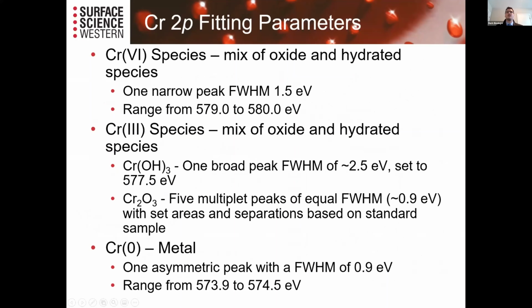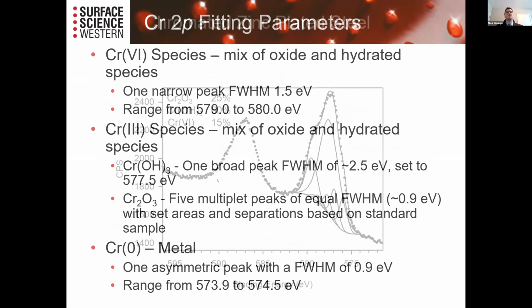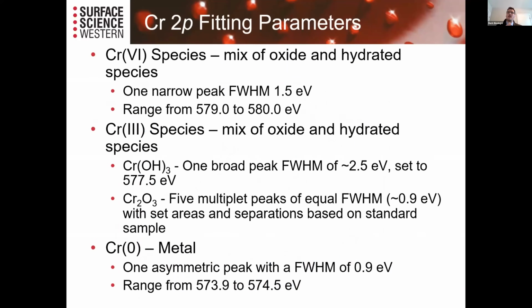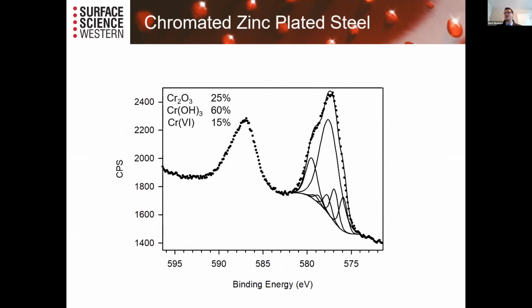For the chromium 3 species, for something like chromium 3 hydroxide, you can fit it with one broad peak set to a specific binding energy and a specific full width half max. For the chromium 3 oxide, you have these 5 multiplet peaks with set spacings, set areas, basically mimicking the shape of the standard sample. And then with the metal, you have an asymmetric peak shape that, again, you mimic for the curve fitting. You put that all together and you can pull out, okay, I have so much chromium 3 oxide, so much chromium 3 hydroxide, so much chromium 6 within a material.